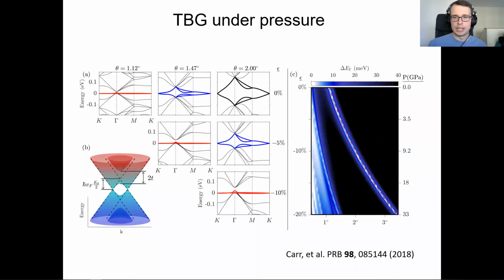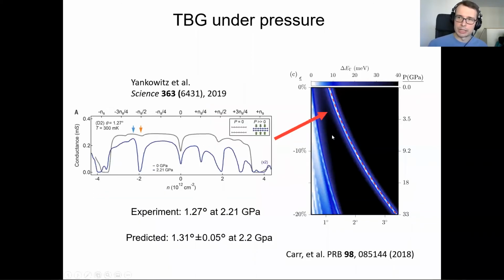the pressure. And Cory Dean's group at Columbia actually did a very beautiful experiment where they made twisted bilayer graphene and then fabricated it in a hydraulic press, and they measured superconductivity and Mott insulation at angles larger than the magic angle by using pressure. And the correspondence was pretty good, kind of fits this linear expansion that we have for our model.